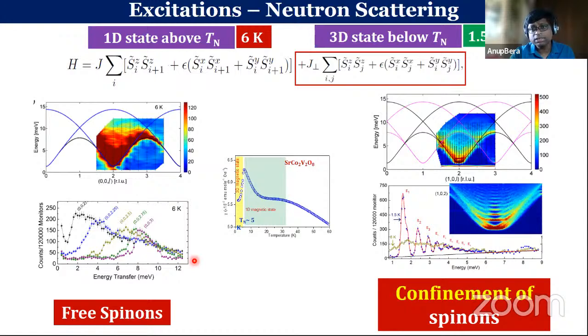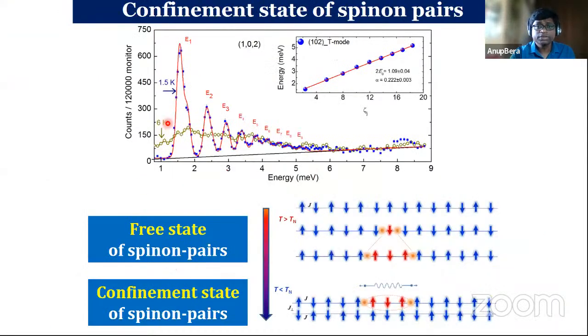Now, how can we understand this phenomenon? It is shown again here. When we are at higher temperature, above the magnetic ordering, by flipping one spin we create two excited quasi-particles, which are known as spinons. Now we can move this spinon without costing any additional energy, because if I flip one spin or three spins, they cost equal energy. And so these spinons are free to move along the chain, and that's why we get that continuum.